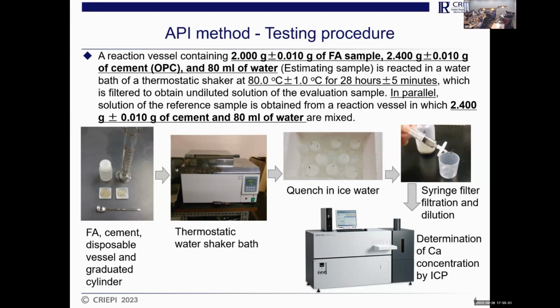This one is for the estimation of the fly ash activity. And in parallel, we need to set a control specimen. It does not contain fly ash, but only the OPC case: 2.4 grams of OPC mixed with 80 milliliters of water. And we must keep it in the thermostatic water shaker bath, like shown in this picture.